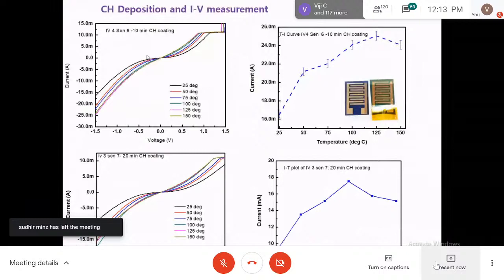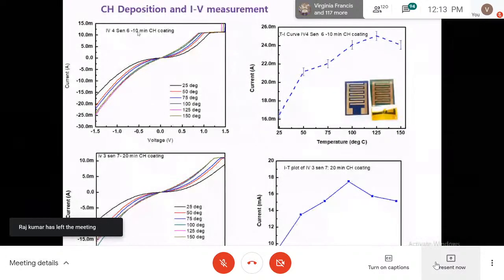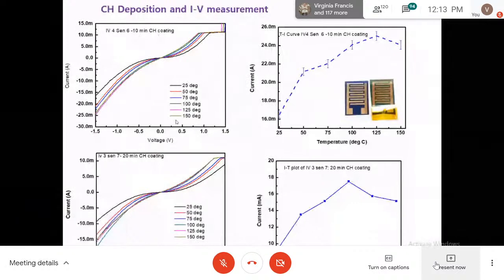Here we can see the 10 minutes cyclohexane coating from 25 degree to 150 degree. What happened? The current value was very high. So this means after the cyclohexane coating, the current value increased. We did not, even now, we did not introduce any gases.